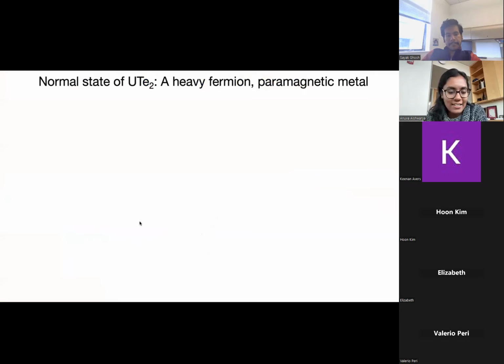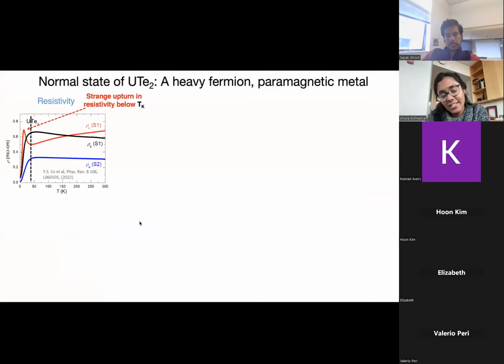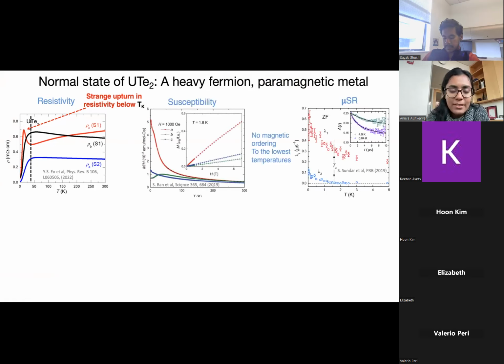So some of the key highlights are as follows. In the normal state, uranium ditelluride is a heavy fermion paramagnetic metal. The resistivity is pretty anisotropic in all three directions. The resistivity drops along the B and C directions after the onset of the Kondo coherent state, which is around 30 Kelvin. However, the C-axis resistivity has a strange upturn well below the Kondo temperature, and I think it's still not clear what the origin of this is. Similarly, susceptibility and μSR measurements show no magnetic ordering down to the lowest temperatures.